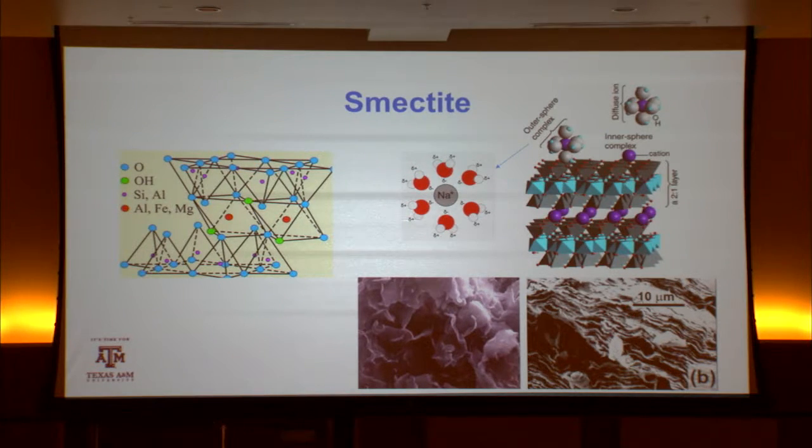This is what happens under desiccation, and if I feed this with a water source, the layers rehydrate, as we've talked about here, and they're pushed apart, and they form this type of structure. So this would be the swollen structure, this would be the desiccated structure. So now we have a good basic picture of why clays swell and why clays shrink, why they're volumetrically unstable.